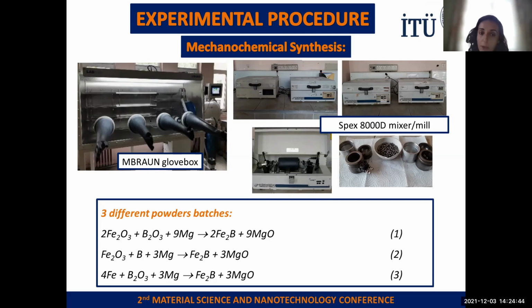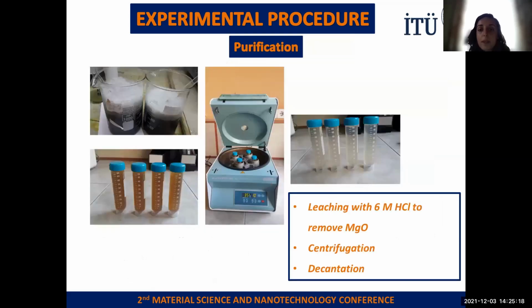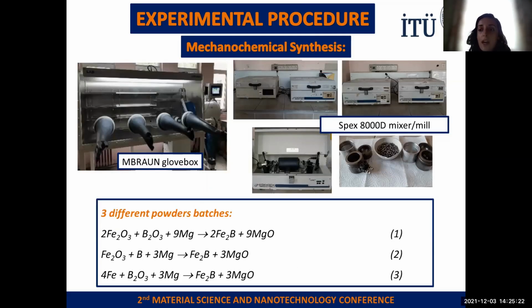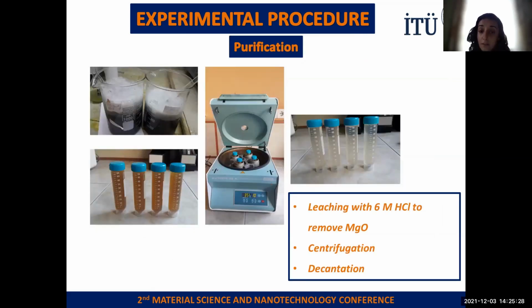These powder batches were filled into the milling vials in a glove box under argon atmosphere to inhibit oxidation of the raw materials. Then the milling vials were closed under argon atmosphere in the glove box and transferred to the high energy ball mills, which run at 1020 rotations per minute during the milling. We milled our powder batches at different milling times, and then